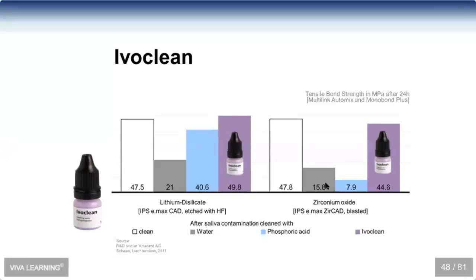The interesting thing is we switch over to zirconium oxide, and you see about the same type of numbers, although you get a bigger drop here because of the salivary contamination. But the real kiss of death for zirconia is if you use phosphoric acid inside the crown. And it's only natural to think that it would. I mean, the zirconia crown kind of looks like the Emax crown, just way more opaque. But that's the kiss of death, because the same thing that causes the salivary contamination, the phosphates in the saliva, it's the phosphates in the phosphoric acid. It's all phosphates. I mean, it's right in the name. It's phosphate acid. And so that's going to really contaminate that crown.